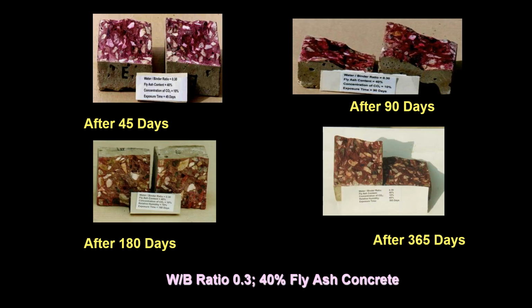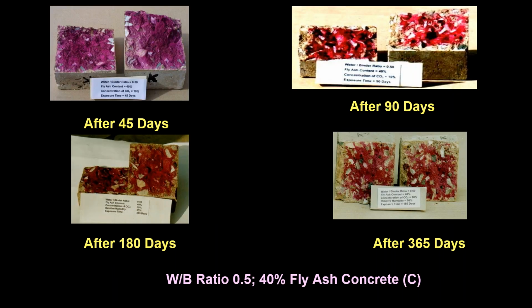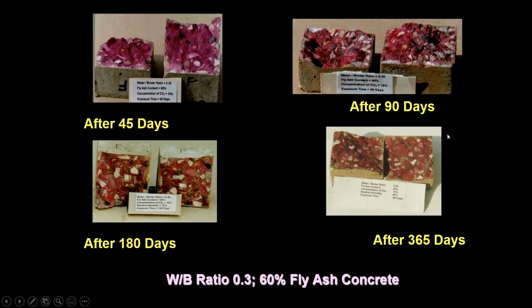And this is 0.3, 40% fly ash, no carbonation. I will show where the carbonation is. Now you can see 0.5 water binder ratio with the 40% fly ash. You can see that on the edges, there is carbonation. I'll quickly show this one.